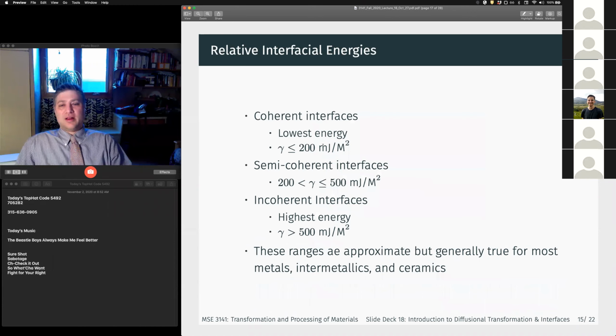So if we look at the relative energies, coherent interfaces in the solid are going to have the lowest energy, so less than 200 millijoules per meter squared. Semi-coherent interfaces generally have a range of about 200 to 500 millijoules per meter squared. And then incoherent interfaces are the highest, right? But anyway, these are approximate, but they're generally true for a wide range of metals, intermetallics, ceramics, right? So just a good starting place to think about this if you don't know the actual values, right? And these interfacial energies are exceptionally difficult to measure.